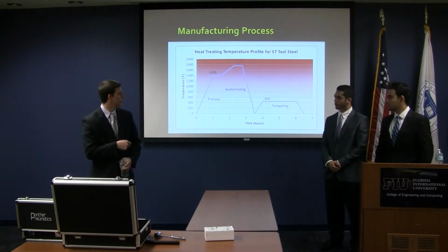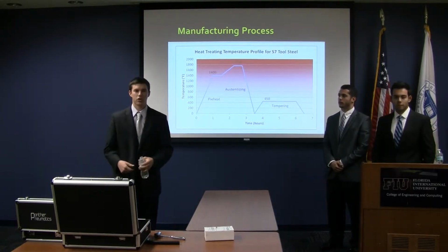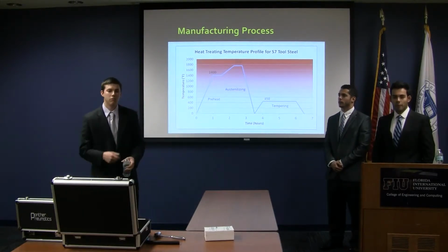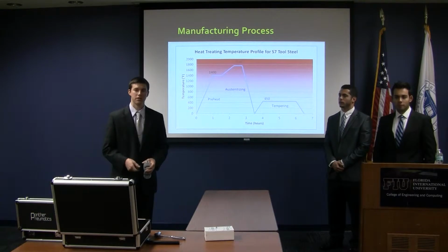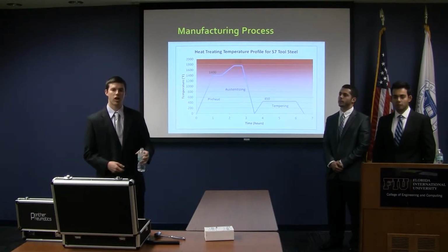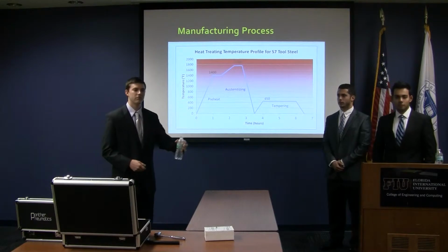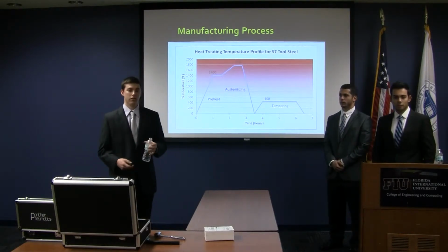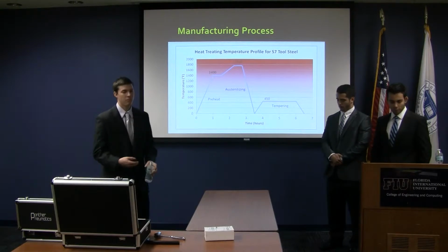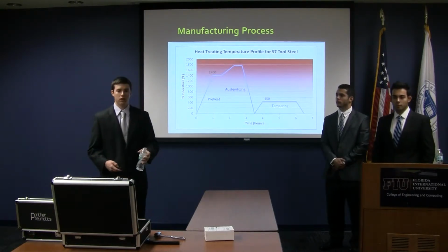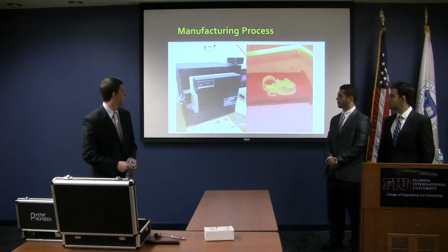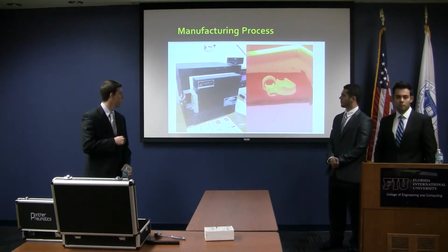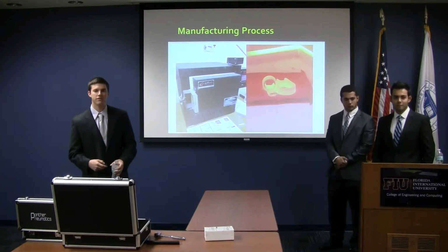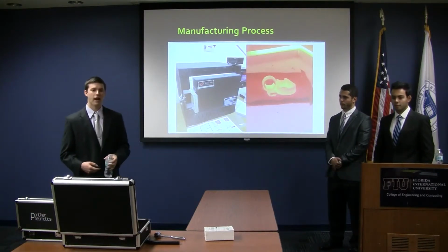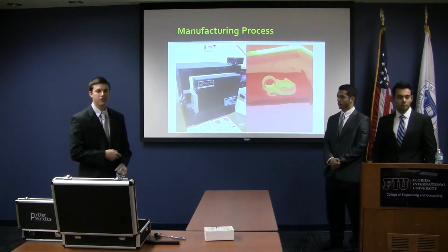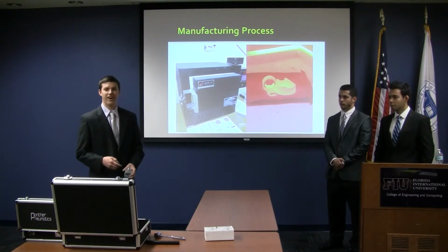And then we bring it out of the oven and right back down to room temperature within a matter of 30 minutes or so, and immediately back into the oven at 450 degrees. This is important to reduce any thermal shock stresses that were induced by bringing it from 1,750 to 0 in a very short time. This also restores some of the malleability of the steel, and produces the final product. And here's some images. This is the oven on the left that we use. This is an open atmosphere oven, no vacuum or no salt bath. These are parts just as we were about to pull them out of the oven. They're very, very hot.